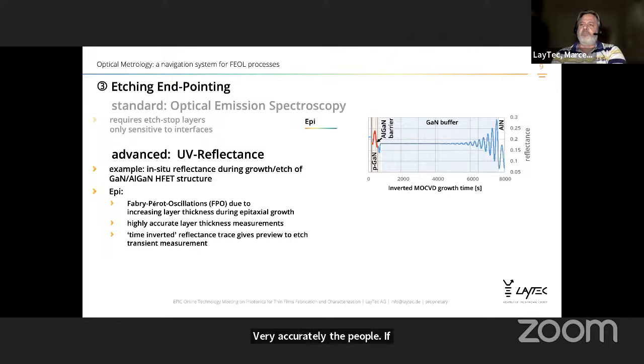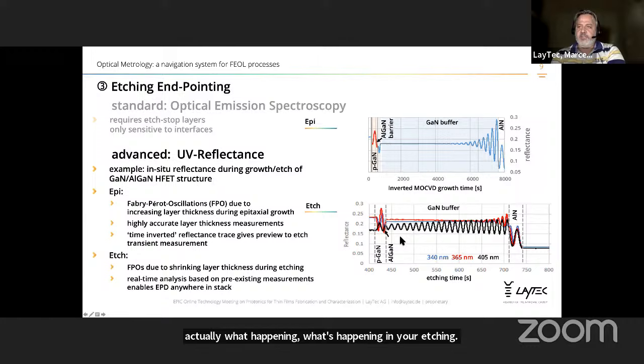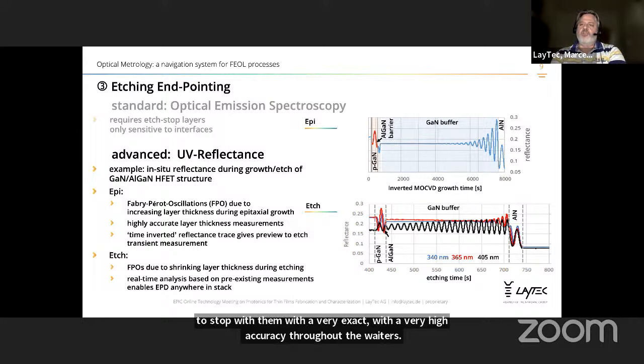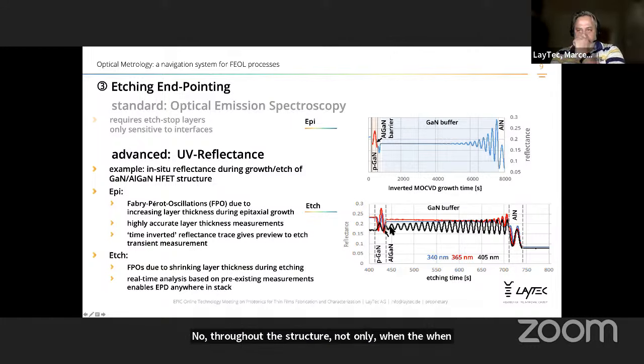If you think of time-reversing this kind of interferogram, you would look first at the pGaN layer, then the AlGaN barrier, and then the buffer. And this is actually what's happening when you are etching the material. And this here is an example of in situ measurement done during the etch-through of an HEMT structure. So at the beginning, we see very clearly the pGaN and AlGaN layers, and we are also measuring at 3 different wavelengths at the same time, and then we can get information throughout the etching process, and basically we can decide where to stop with very high accuracy throughout the wafers, throughout the structure, not only when there is an interface there.